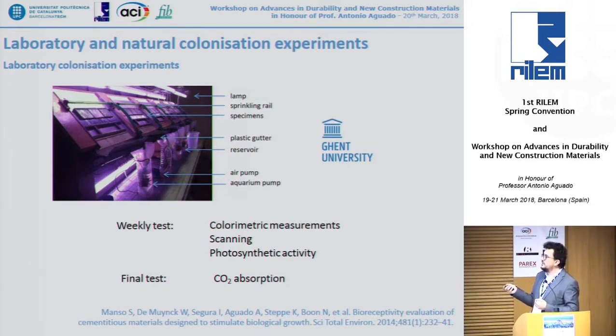And we made colorimetric measurements, scanning images, and photosynthetic activity in order to control the growth of the colonization in our samples. And also we made CO2 absorption at the end of the test in order to evaluate in which of the materials you have the largest biological colonization.